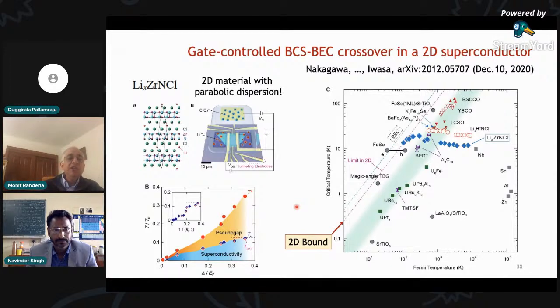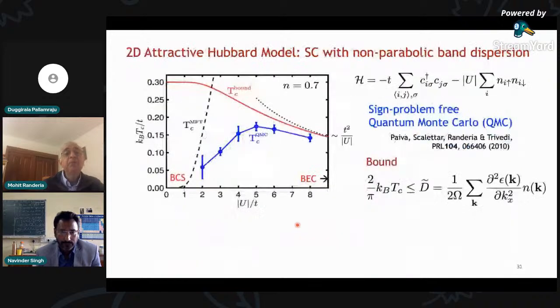You see, the thing is that you only need to change the interaction relative to the Fermi energy. So in cold atoms, for fixed density, you can change the interaction. In the solid state, there's no such knob. So what they did was, okay, we can't do anything about the attractive interactions of the system. We'll change the density by a huge amount, which is not easy to do in a metal. But they did it by doping a band insulator. And these are their data, the blue diamonds. And you can see that they basically approached the 2D bound of 0.125 in their TC. So which says that now there are systems where you can reach the 2D bound.